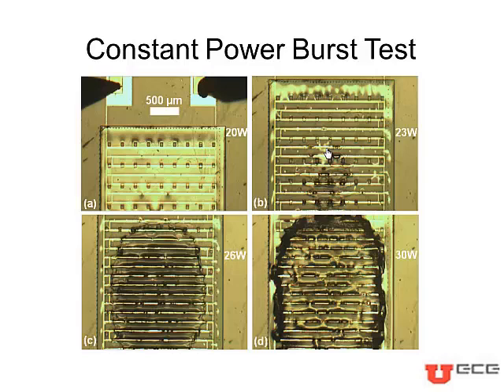In the constant power burst test, a DC power supply was directly connected to the aluminum heater, and the damage on the chip was monitored using a video camera. The parylene melted at different voltages, and these pictures show the melting of parylene at different applied heater powers. The melting of parylene starts at about 20 watts, and by the time we reach 30 watts, almost all the parylene of the bottom wall melts.